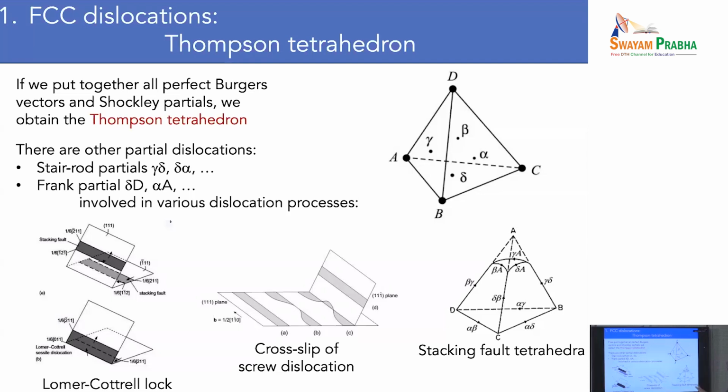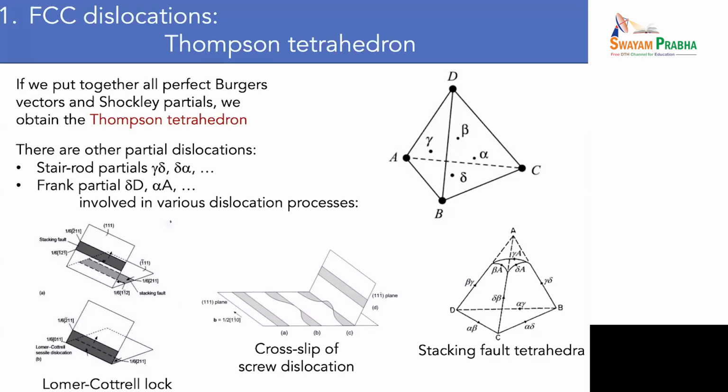And then there's the so-called stacking fault tetrahedra, where in FCC, if you form a vacancy loop with a triangular shape, all of the edges can dissociate, and by magic, when you look at all the dissociations, on every side of this triangle with the dissociation and reconstruction, you only form Lomer-Cottrell segments.